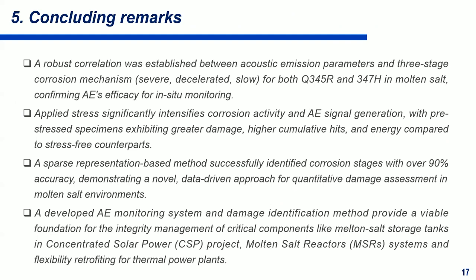With stressed specimens exhibiting greater damage, higher cumulative hits and energy compared to stress-free counterparts. A sparse representation-based method successfully identified the corrosion stage with over 90% accuracy, demonstrating a novel data-driven approach to quantitative damage assessment in molten salt environments.